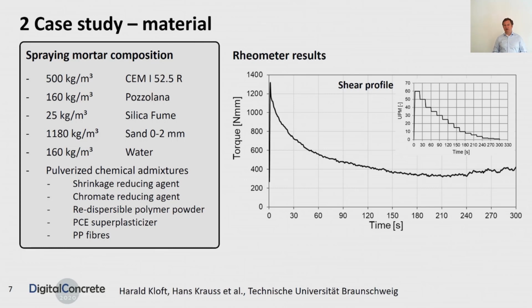However, we need such a complex material in order to match the rheological requirements for pumping, spraying, extrusion, and for the fast structural buildup after application. As you can see in this diagram, the material we used shows an excellent structural breakdown under shear, and, not shown in the diagram, it also evidently exhibits a very fast structural build-up after application.